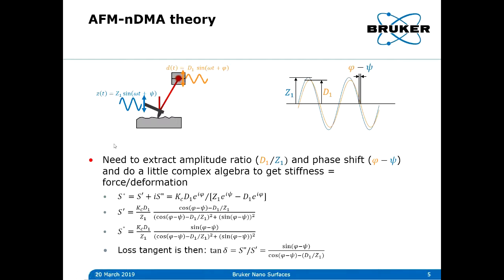Once we've done that, we do some basic complex algebra, and we get a stiffness, which is just the force divided by the deformation of the material. If we separate out the real and imaginary parts, we get some real and imaginary stiffnesses, and we can take the ratio of these two stiffnesses to get the loss tangent directly.